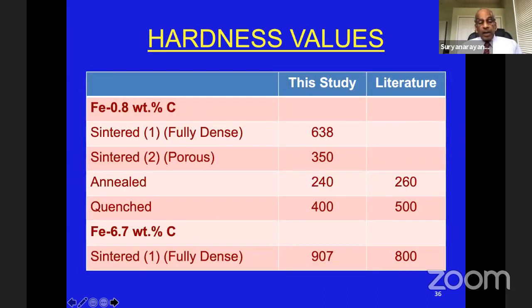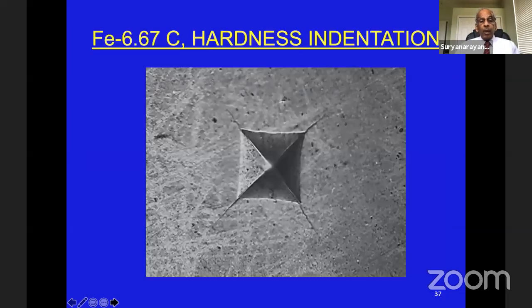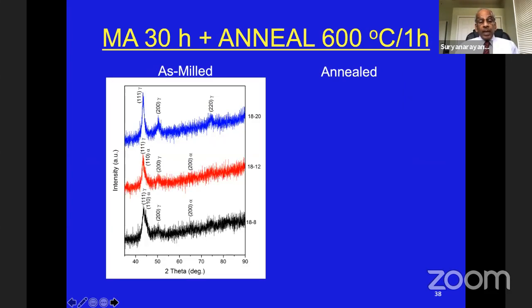I can measure the hardness values, and when I measure the hardness values, if it is fully dense, the pearlitic steel has a hardness of 638 Vickers. And if it is cementite, 900 Vickers hardness number. By annealing and quenching, you can adjust the properties very easily. And if you look at the hardness indentation of the cementite, you can see all these cracks indicating that the material is relatively brittle.